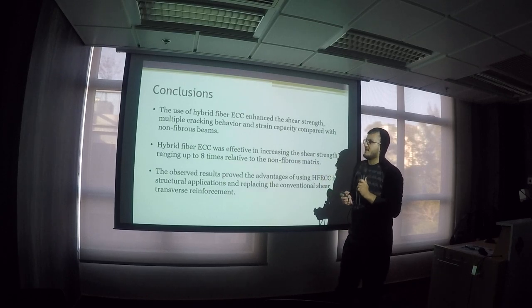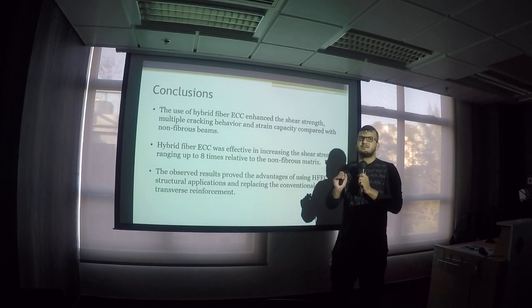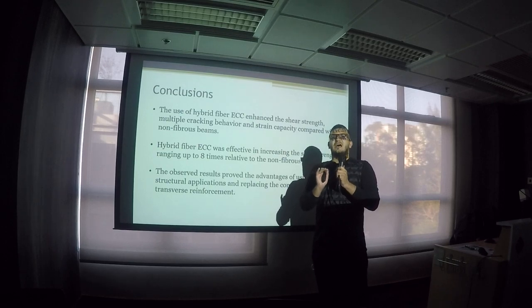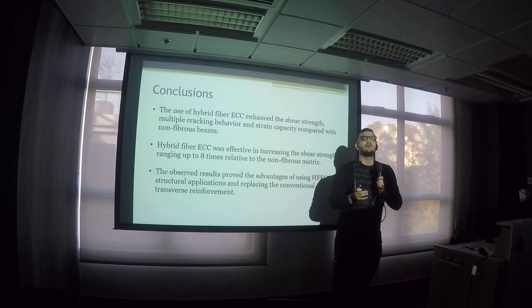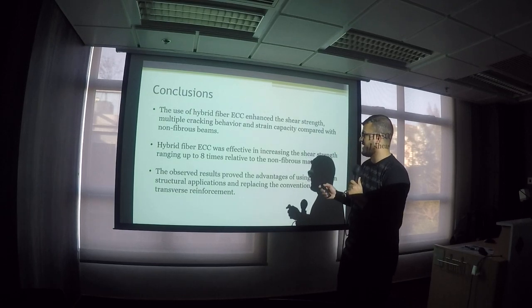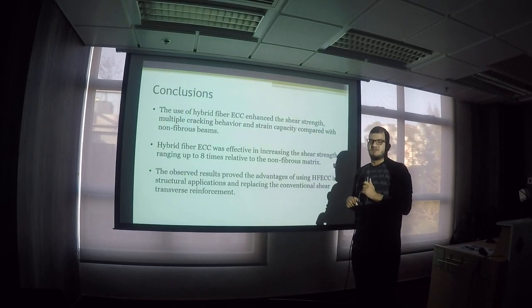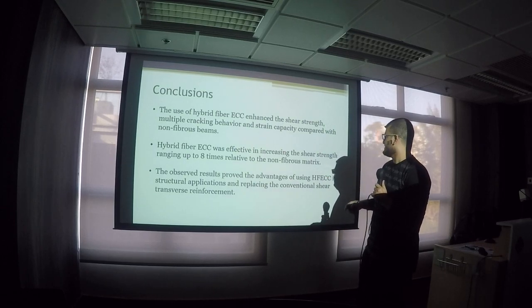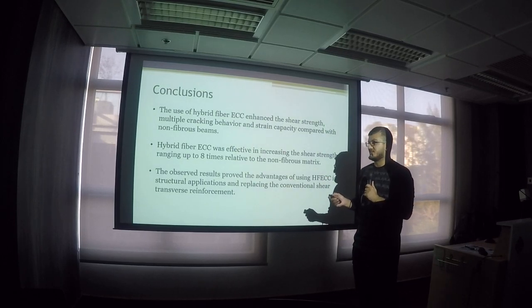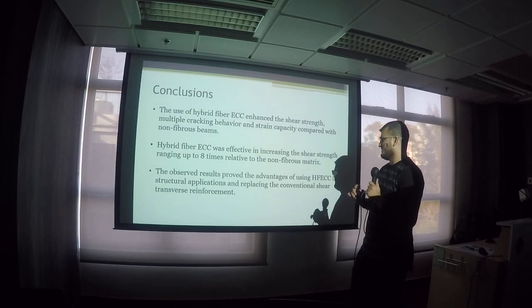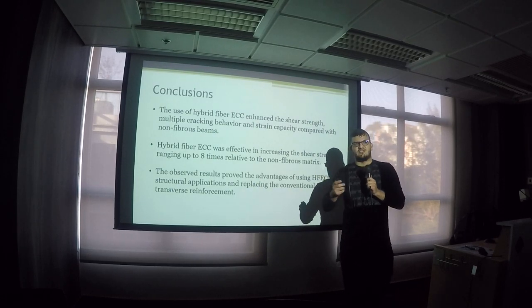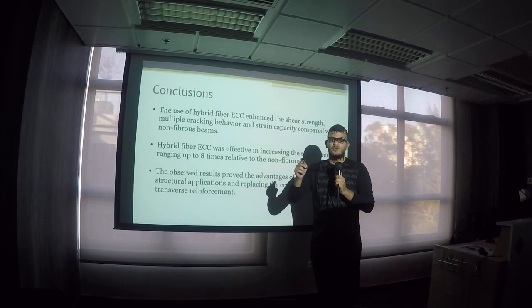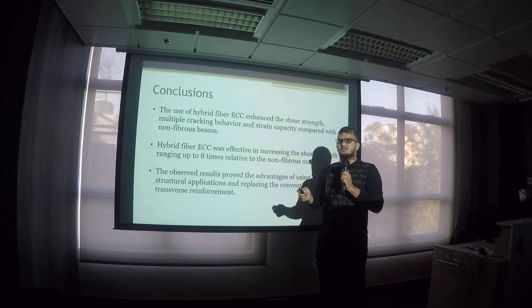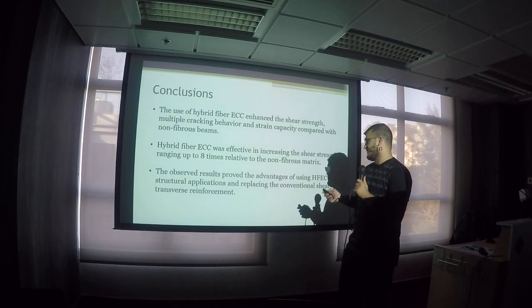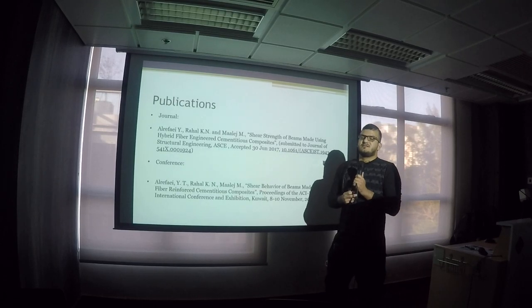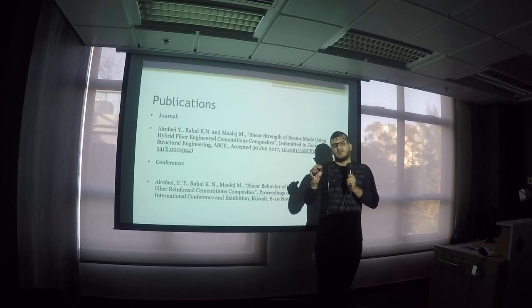So at the end, let's make the conclusion that the use of ECC materials in the beams enhanced the shear strength. Why? Because it enhanced the multiple cracking behavior and it enhanced the strain capacity relative to the non-fibrous beams. Again, the shear strength was increased up to 8 times, as I previously mentioned. So all this research and these findings prove that using ECC materials in structural applications is really a good advantage in structures. So this is just a brief of my research work.